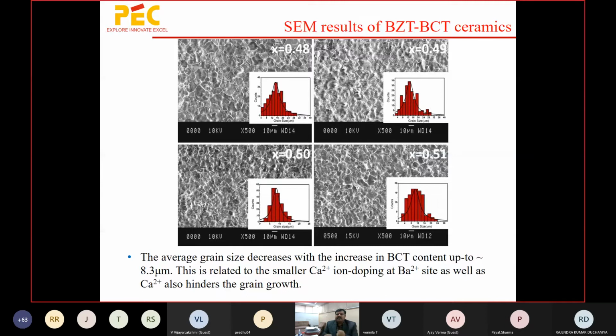And these are the SEM micrographs of these BZT-BCT ceramics for different compositions. What we observe with the increase in BCT, barium calcium titanate, is that we are replacing zirconium with calcium, and calcium has a smaller size than barium. We are doping this calcium at the barium site, and because of that the grain size got reduced. In every SEM micrograph, we have shown the histograms for the grain size, right? For x equal to 0.50, it is nearly 8 micron, and for other compositions it is more than 10 micron.